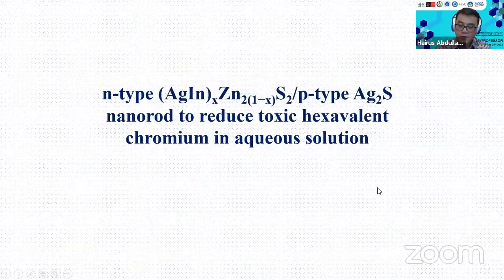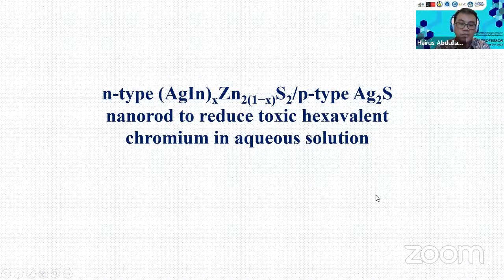Okay, then the second part that I want to show you is the PN heterojunction. PN heterojunction to reduce the toxic hexavalent chromium. So in this case, this is the zinc sulfide based material. We dope with the Ag and In metal and make the band gap become lower. Then to make this material more efficient, we couple with the p-type Ag2S, which has a lower band gap, and this can make the efficient electron transfer and hole transfer during the reaction.